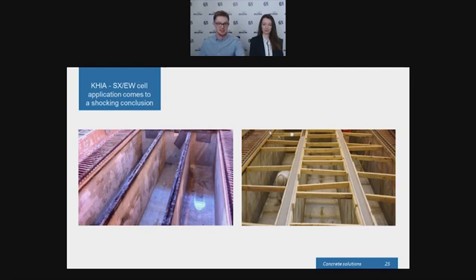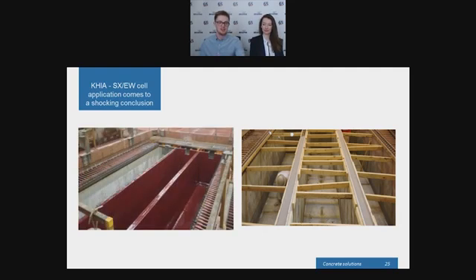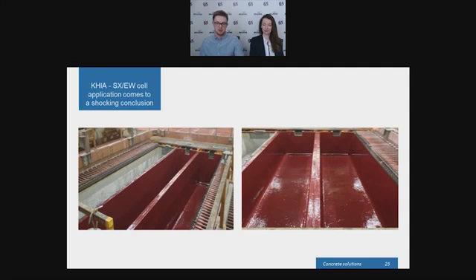So this prevented the sulfuric acid from even getting to the concrete or getting to the Belzona underneath in the first place. And if you can prevent it from getting there in the first place, you prevent the damage from happening. The customer was so happy at the end, after the coating job was finished, that they actually supplied this and applied this onto 100 other containment cells as well, just proving that the solution was one which they were very much looking to invest in because it was a workable solution.